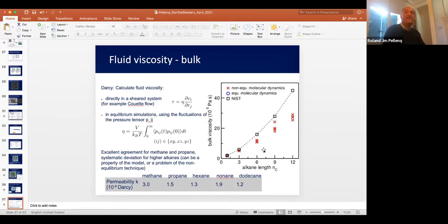So eta from statistical physics, in the bulk, is what's called the Green-Kubo formulation. This is basically the time autocorrelation of the pressure tensor. You calculate this integral, and this is the statistical physics formulation of the viscosity, fine, and we can compare the bulk with experiment. I mean, yes, with data from NIST, for instance, and we are not crazy bad, fine. Meaning that if we know the flux, if we know the pressure gradient, and if we know eta, we can calculate the permeability for this nanoporous material.